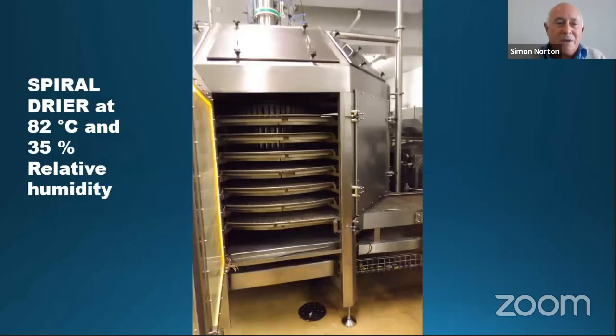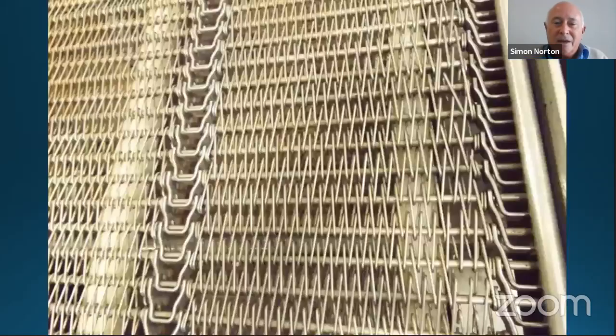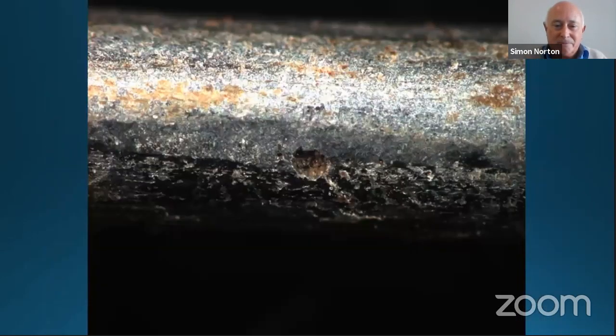So here we go. There is the dryer that dries the sausages at 82 degrees centigrade and 35% relative humidity. There's the conveyor belt on which the sausages move. And all these wires started to break. Little pieces of wire were then found in the sausages, and there was a complaint from customers.